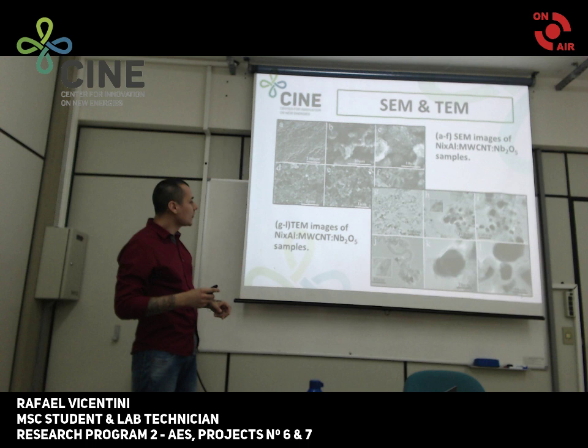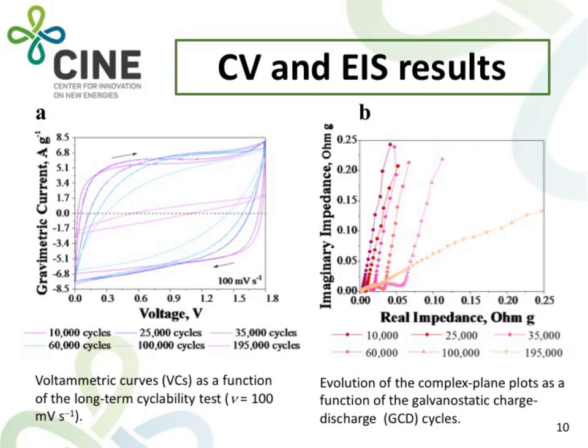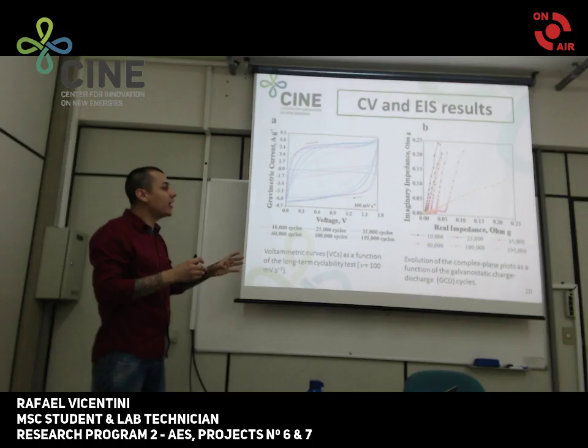Let's look now to the electrochemical studies. First, on the left side of this figure, we have the cyclic voltammetry, or the voltammetric curves, as a function of charge and discharge cycles. And in figure B, we have the evolution of the complex plane plots as a function of charge and discharge cycles. Here, in both cases, it goes from 10,000 cycles to 195,000 cycles.